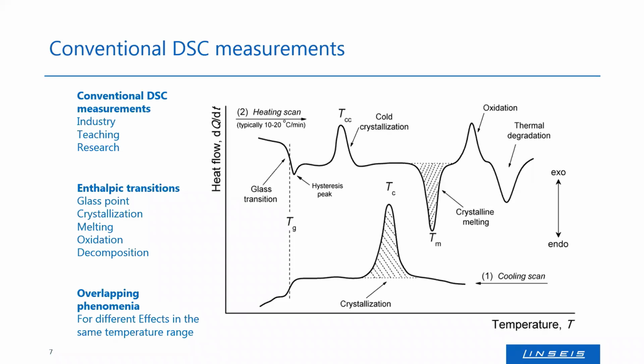That's a heating and cooling scan of a polymer. What we can see there is a glass transition in the heating run with the hysteresis peak or a relaxation peak. The next thing is the exothermal cold crystallization. Then, of course, the melting of the polymer. And then you can choose with or without oxidation, the oxidation itself, or the decomposition, the thermal degradation.